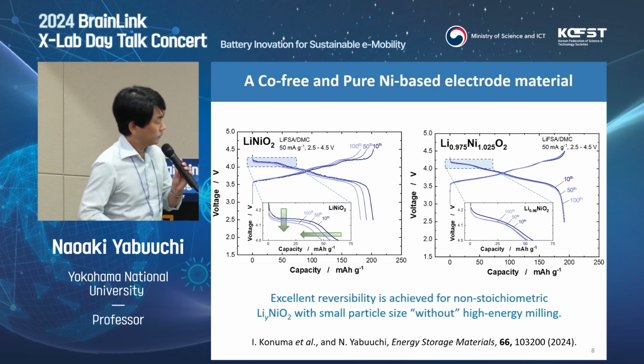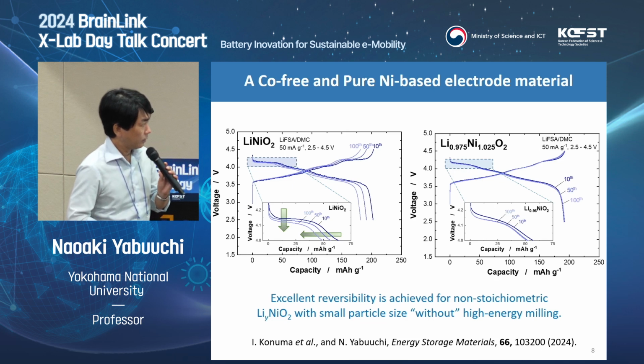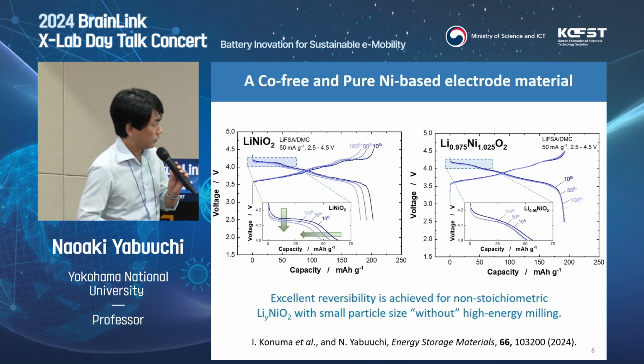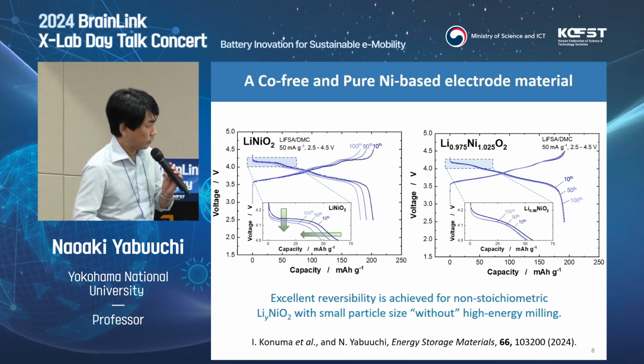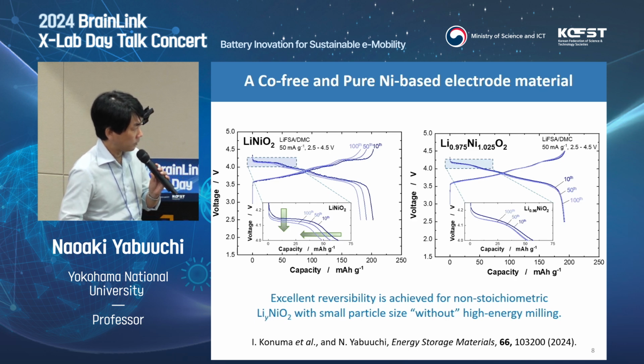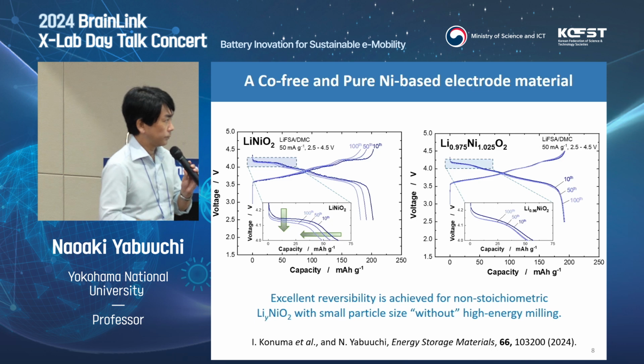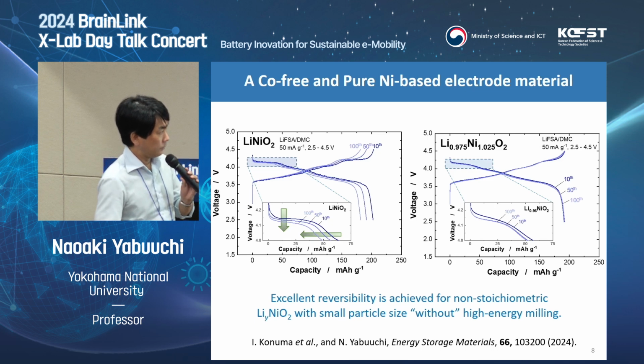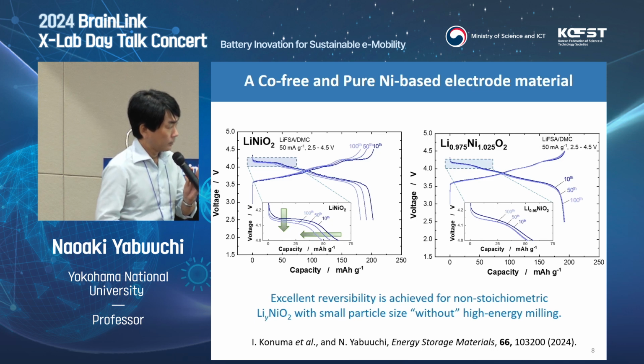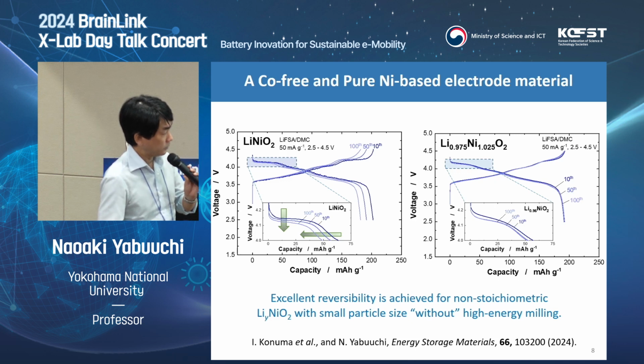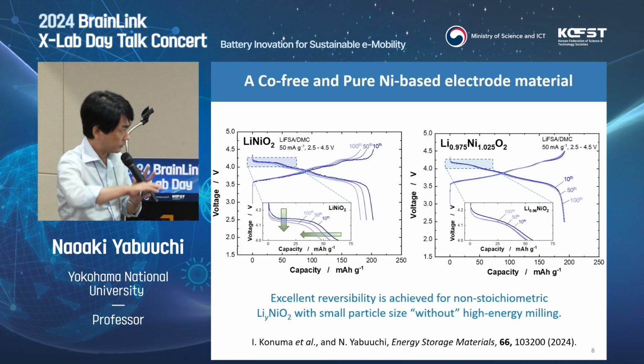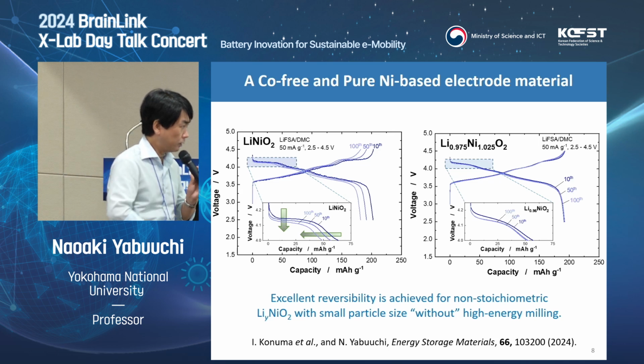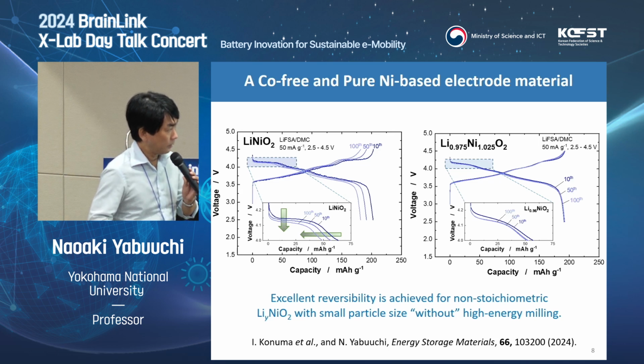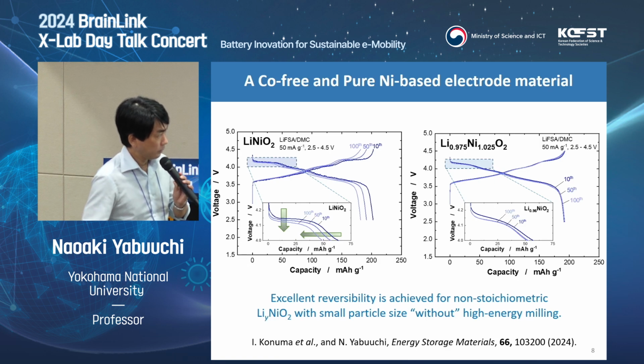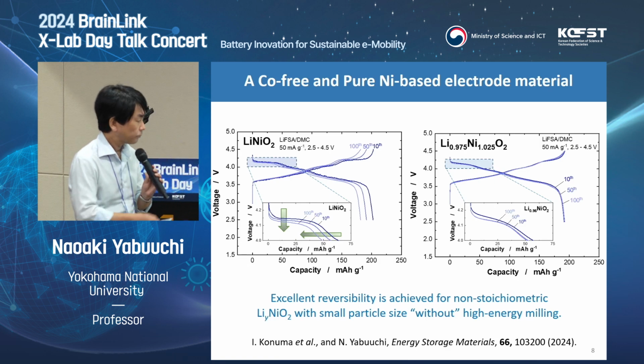However, if you see high voltage regions, the degradation process is essentially the same. You can see an increase in impedance at the high voltage region, and loss of reversible capacity. However, for the lithium deficient samples, reversibility is now very, very good with a highly concentrated electrolyte solution because of improved surface passivation stability. So now you can get very high reversibility, with no capacity fading for 100 cycle tests.